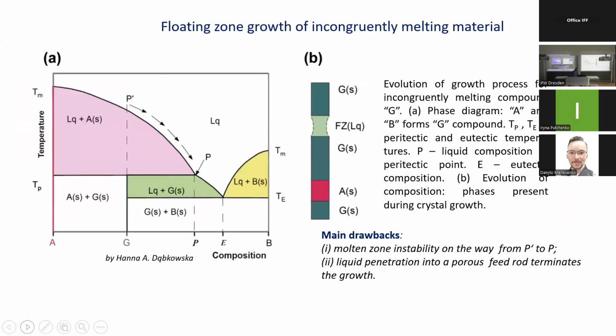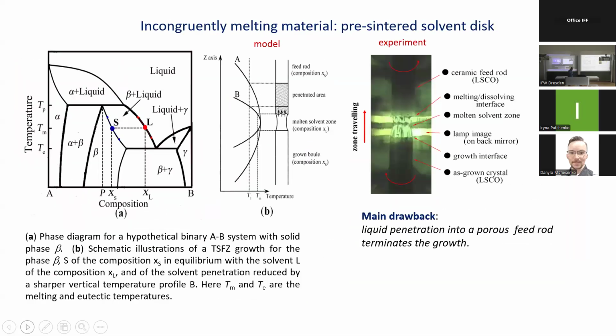Porosity mainly depends on the sintering temperature. If it's relatively high, above 1400 degrees, then you get a high density feed rod, about 90% of theoretical density, and then the penetration effect is very weak. Why is it better that it doesn't penetrate? Because otherwise you get no liquid in the molten zone. It sucks all the liquid from the molten zone. It just breaks the process. Yeah, exactly, it terminates the growth.